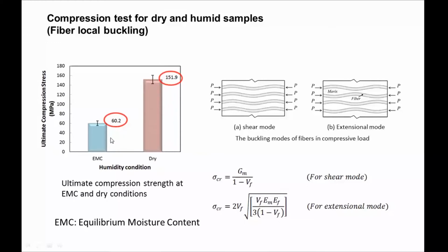For the humid samples at the equilibrium moisture content, about 10%, you can see about 60 megapascal. But if you dry the sample, you can see 152 megapascal, and it can be justified due to the buckling of the fiber inside the matrix and the relation of the volume fraction of the fiber and the shear modulus of the matrix, and you can see the effect of the modulus of elasticity of the matrix and the fiber, and the volume fraction of the fiber. With humidity, we have less EM and less EF and also less shear modulus of the matrix.